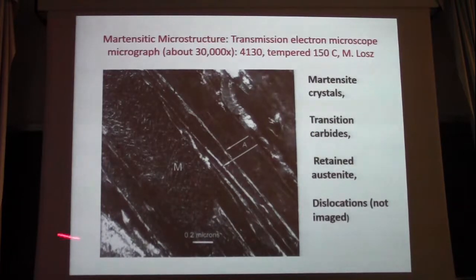Now, to see the fine structure requires electron microscopy. This is a dark field image, taken at 30,000X. And so now we can see even the smallest martensite crystals. And since this is tempered at 150 degrees C, these small white patches here, those are the transition carbides that help to create high strain hardening of the martensitic structure. In these martensites, here's the leftover austenite. The leftover austenite is in between the fine crystals of martensite. And what is not shown is the dislocation structure that is the backbone of ductile fracture, ductile behavior, high strength behavior in these quench and tempered steels.